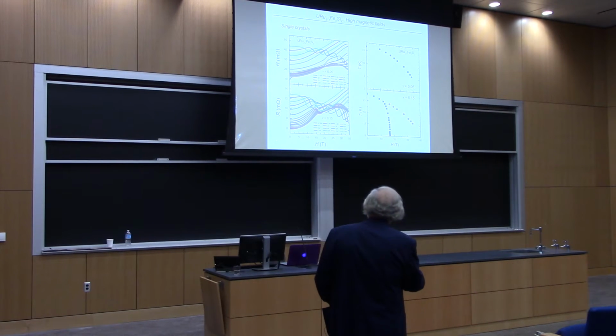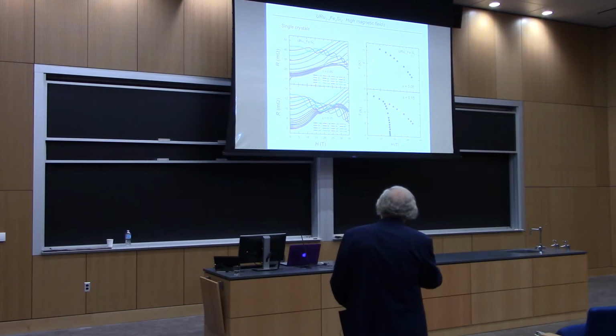These are measurements for iron substitutions that we've been making at the National High Magnetic Field Laboratories in Tallahassee and Los Alamos. So here are the features you see up to 35 Tesla. And as you increase the field in the hidden order phase, you see the decrease of the phase boundary like this. And then in the antiferromagnetic phase, you actually see this part, this is the suppression of the antiferromagnetism, and this part that's due to the hidden order.